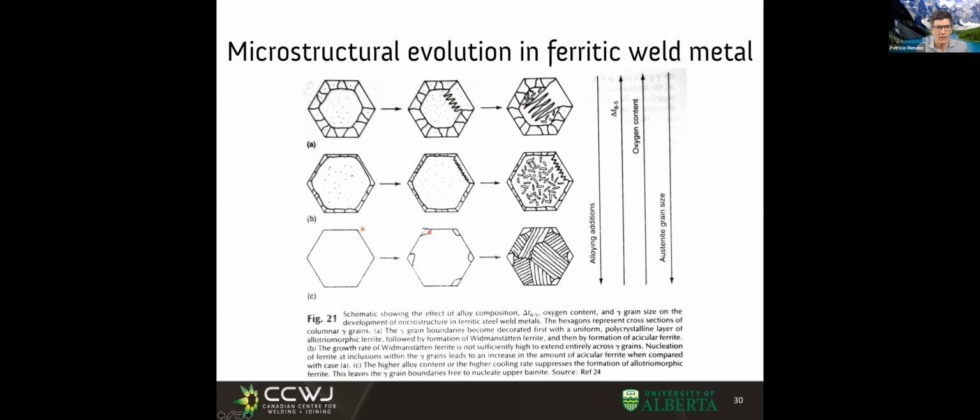Now, the triple points in the grains, these corners in the hexagon, actually represent points in which we have three grain boundaries meeting. The grain boundary of this grain against the one that would be here, and against the other one, the grain that would be here. Here they didn't draw a line, but there is another grain boundary. So at those triple points, which would be the most powerful nucleation sites, we can have some primary ferrite appearing.